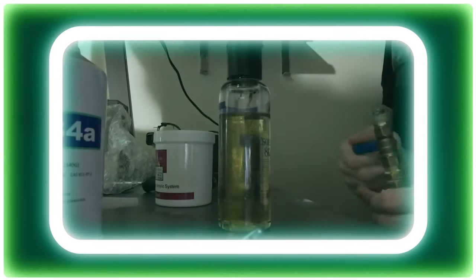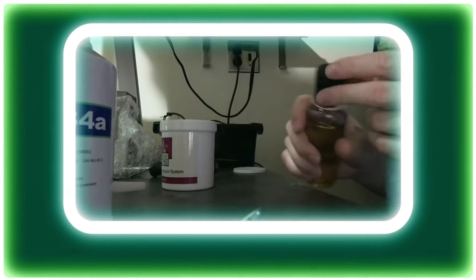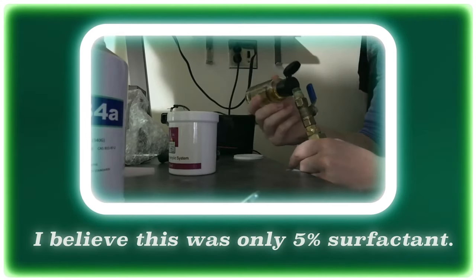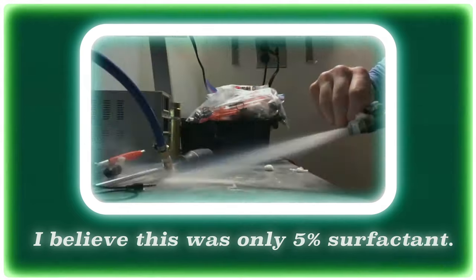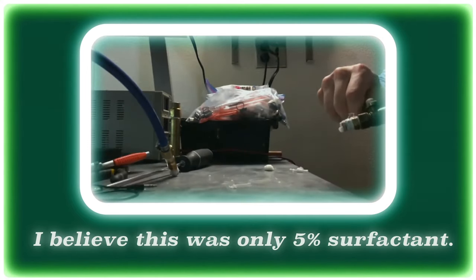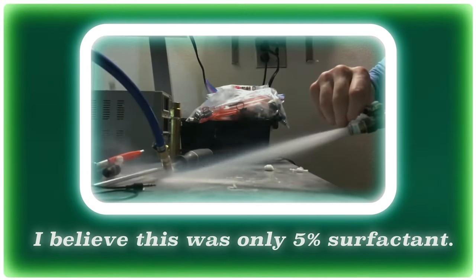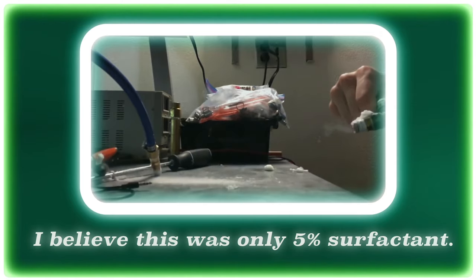For instance, in this test from my web fluid tutorial in 2017, I added a really small amount of surfactant, and when the web fluid was shot, it maintained its liquid state for a very long time, was extremely sticky, and was able to be shot rather quickly. In these tests, also from 2017, I added a really small amount of solvent with a higher amount of surfactant. Now, this web fluid came out with larger expanded diameters, almost instantly solid, not sticky at all, and only oozed out slowly from the nozzle.